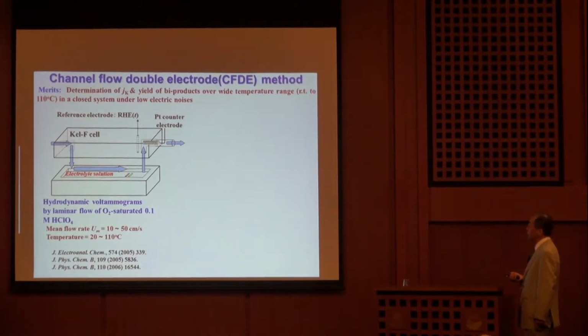And also, we developed the channel flow double electrode method, which allows us determination of the kinetically controlled current and also the yield of the byproduct over a wide temperature range, from room temperature to beyond 100 degrees Celsius in a closed system under low electric noises. The cell has a very narrow gap, less than 0.5 millimeter, and the electrode placed here. The size is 1 millimeter, 1 centimeter, very small size.